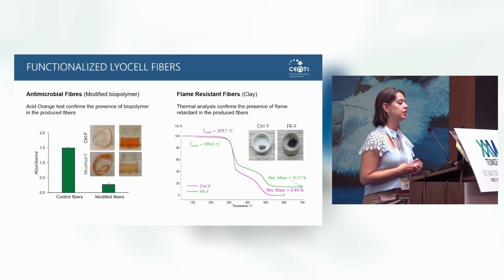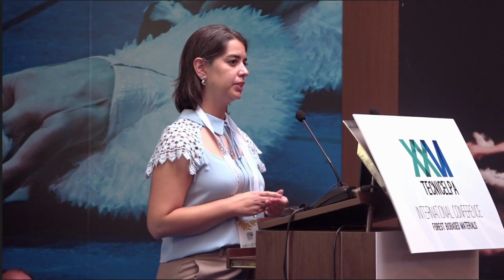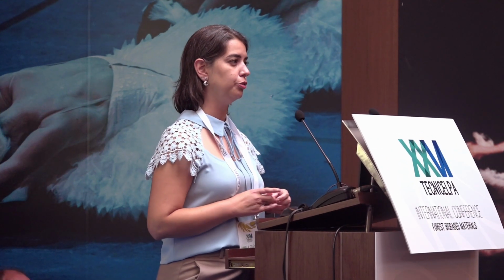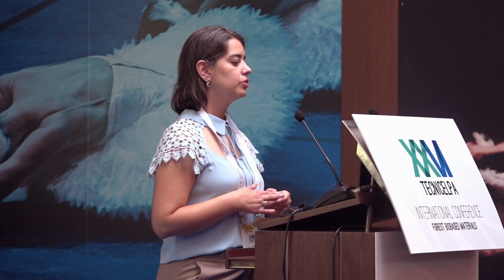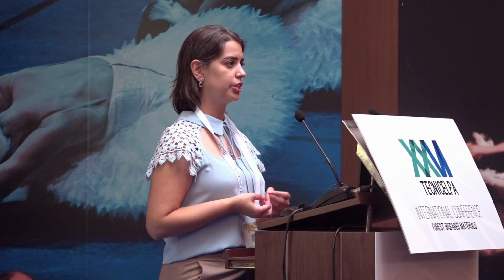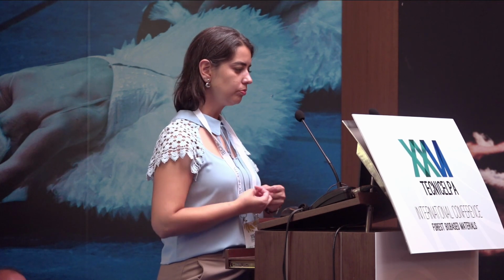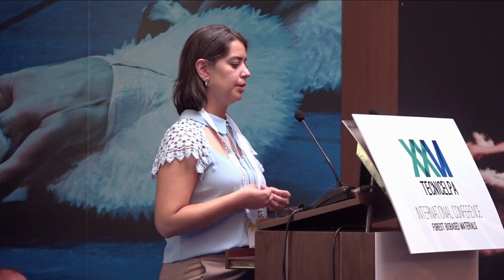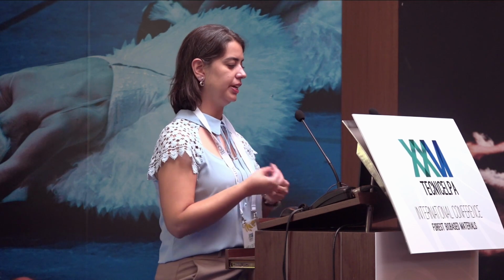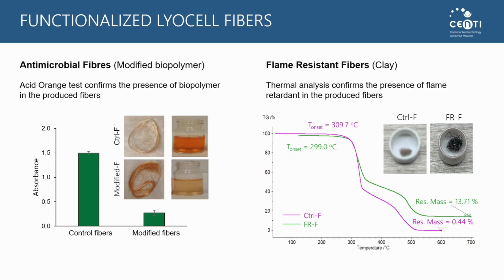To prove the presence of the additives in the fibers, in the case of antimicrobial fibers, we used a spectrometric method based on UV absorption. So we used the acid orange dye that has absorption interaction, preferential interaction with the biopolymer.